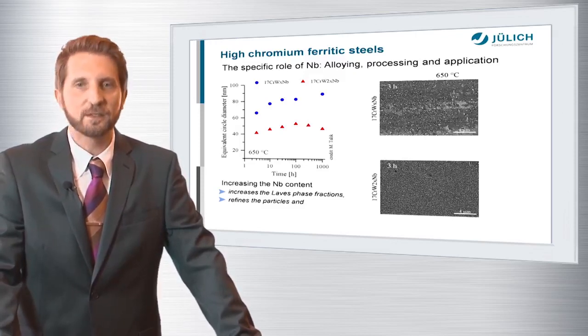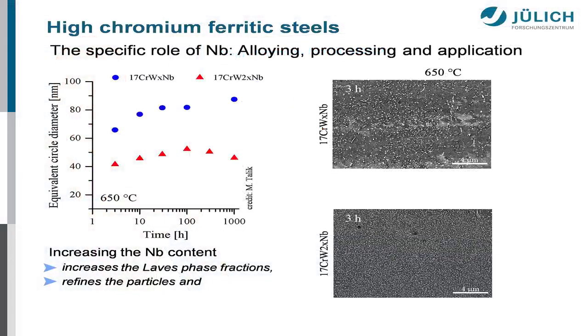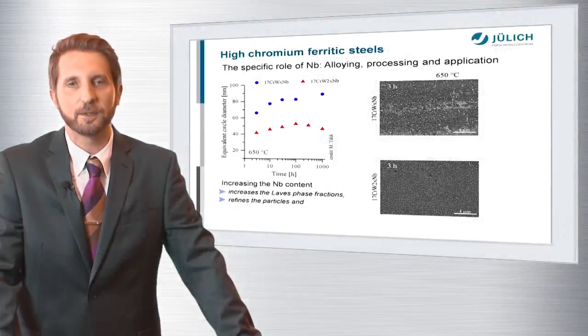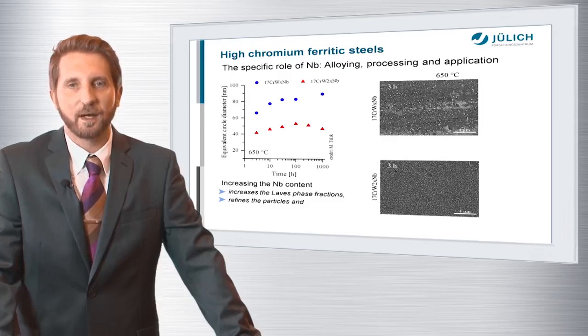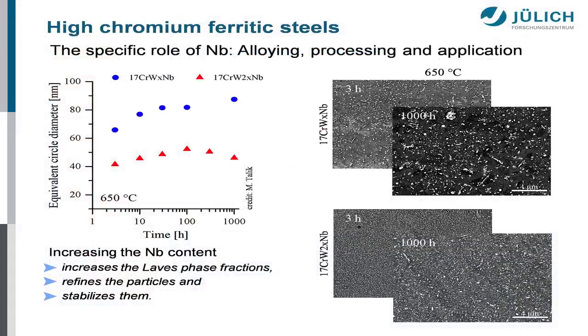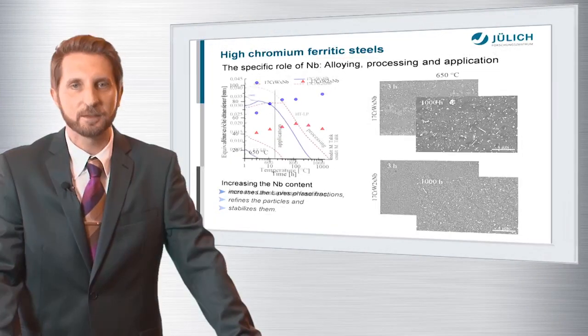And what you can quite nicely see is that the alloy with the higher niobium content forms much smaller particles, which is reflected in the particle diameter that you can see as a function of time in the diagram. So the blue curve is for the single niobium alloying, the red curve is for double niobium content, and you see the particles are much smaller, and obviously in the long term, up to 1,000 hours right now, the higher niobium content seems to be beneficial for stabilization of the particles, what can be quite nicely seen in the micrographs that were taken after 1,000 hours. Double the niobium content leads to less coarsening of the particles, and that is very beneficial for long-term application of such alloys.